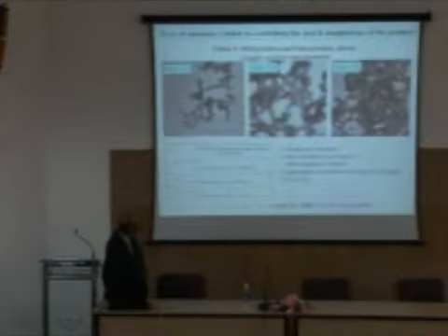We have explained that as the carbon chain length increases, the intermicellar exchange rate increases and the size increases till a certain level. Beyond a certain length of the carbon chain, they start interacting with the surfactant, and again the size reduces. So this is kind of a repetition of that.